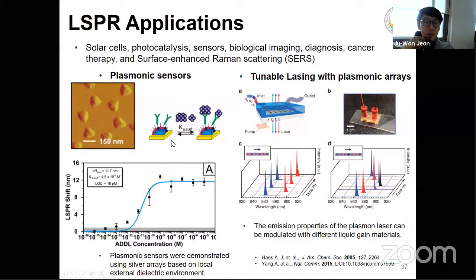In this case, the silver array was decorated with a ligand for specific chemicals, and consequently this plasmonic nanostructure could detect the existence of the specific chemicals based on the LSPR shift, because there is an interaction between the ligand and chemicals, and then the changed environment gives a different LSPR position of the nanostructure.